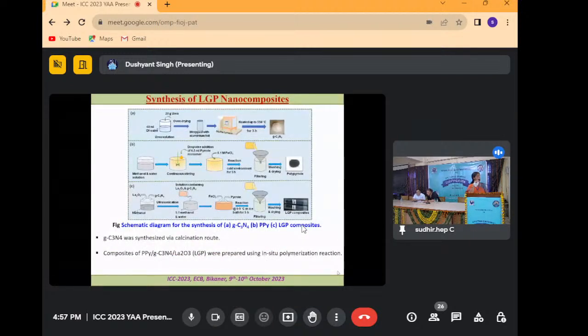So this is the synthesis process of the LGP nanocomposite. The graphitic carbon nitride was synthesized via the calcination route, and these nanocomposites of polypyrrole, GCN and lanthanum oxide were prepared using an in situ polymerization reaction. In the steps we can see here, first GCN is synthesized from urea, and then LGP and MGP composites have been synthesized using the in situ polymerization reaction. These are the basic steps used to synthesize these nanocomposites.